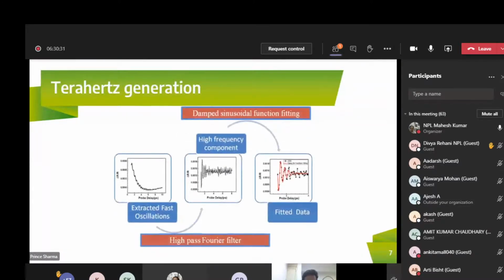These kinetics are analyzed using this given process, and we term this process filtered high frequency component followed by fitting data. In this process, we extracted the fast oscillation which is between 1 picosecond to 10 picosecond, and using the high pass Fourier filter, we filter out the oscillations from the decaying profile of the charge carriers. These filtered oscillations are then fitted with the sine damp function, and the fitted data give us a frequency which lies in the terahertz regime in case of a topological insulator.